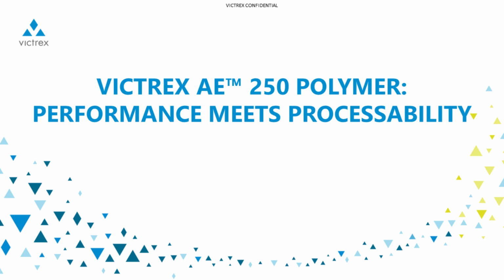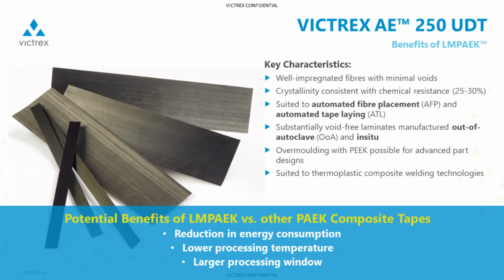The UD tape format is really interesting, and the way that we produce this tape allows us to provide this well impregnated, low void content, relatively high crystallinity tape that can be used to create parts. And when it's made from the low melt PEEK product, it has a 40 degrees Celsius lower melting temperature than a traditional PEEK. So that opens up some benefits, including reduced energy consumption, which is also related to lower processing temps. And we found a really robust processing window.